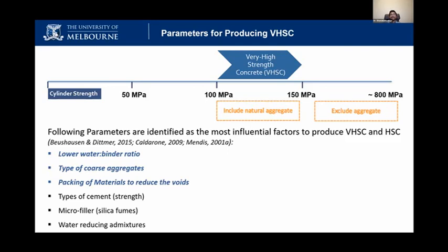Then the cement, of course, is a critical factor, the grade of the cement. Then I would say another most important criterion is the silica fume. Even though we pack it properly and reduce the water to binder ratio, there is still a lot of porosity in the structure, especially at micro scale. In the presentation, I will show how porous concrete actually is. It's more porous than we think. So this micro filler, silica fume, fills the micro gaps between the particles and increases the strength.